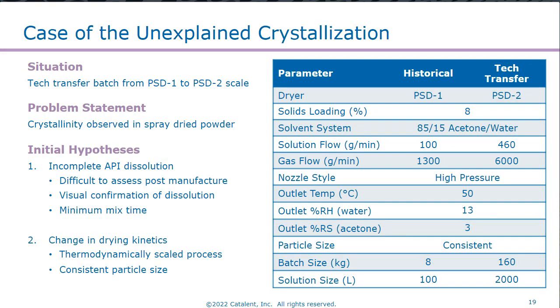Now I'm going to walk through a specific case of some troubleshooting we saw during tech transfer of a batch from the PSD1 scale to the PSD2 scale, where we had no historical observations of crystallinity in our spray-dried powder until this batch. There were a few initial hypotheses on what had happened. The first one was incomplete API dissolution. An issue with this hypothesis is that it's really difficult to assess post-manufacture. Once that material's been sprayed, we can't go back in time and assess if it was fully dissolved in the